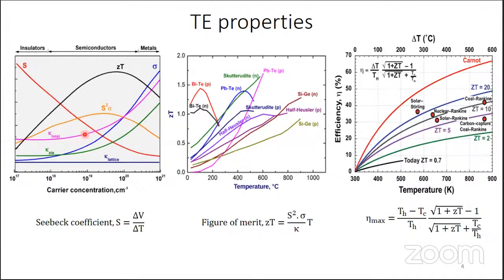And then you have to create a delta T across the material. So the material should have low thermal conductivity also. If the material is like a metal, with high thermal conductivity, you cannot create a temperature difference across the material. So you cannot create thermopower, and you will not have any thermoelectric effect. So all these characteristics, which in a way oppose each other, have to be optimized to get a parameter called ZT, that is the figure of merit, which consists of S squared sigma by kappa. That is, S squared sigma is called the power factor, divided by kappa, that is thermal conductivity. This factor should be a reasonable value, as much maximum as possible.